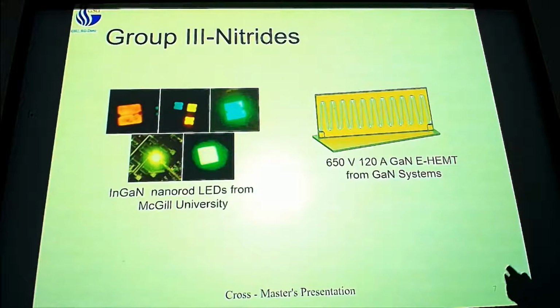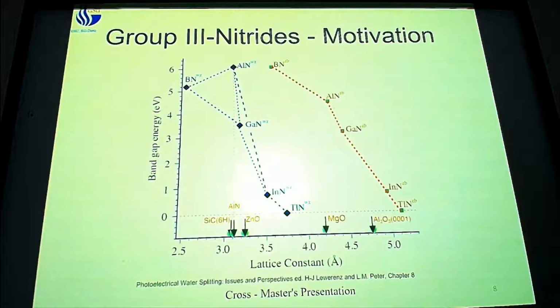They also have made, and I couldn't find a nice picture of this that I could guarantee was nitrides, solar cells. They're working on making higher efficiency solar cells with these materials, which we care about because they fall in the same system and have a very similar lattice structure with a large range in band gap. Starting down here at indium nitride that I work with, 0.6, 0.7 eV as a band gap, going all the way up to about 6.1 within the same material system. So we have indium nitride, gallium nitride, and aluminum nitride that all have a very similar lattice constant, which is the size of the crystal, with a very large variation in the energy band gap. So we can start thinking about these materials to make sensors that are variable from infrared all the way up to UV.